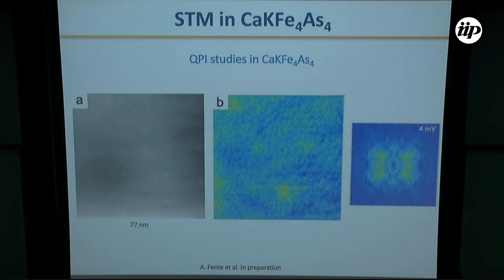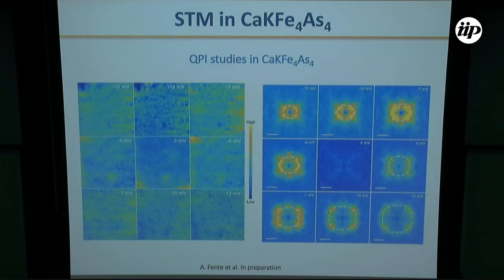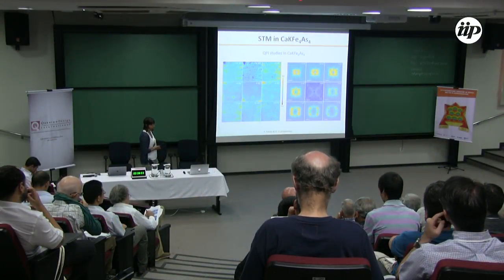We have made the QPI study in this sample. As I mentioned before, we first look at a large atomically flat region. Then we make conductance maps at different energies, and we analyze the quasi-particle vectors that appear in the Fourier transform. Here I show you the different images that we obtain as a function of energy between minus 13 millielectron volts and 13 millielectron volts, and the corresponding Fourier transforms, where we can identify a QPI vector that increases when we increase the energy. You can also note that at the Fermi level, the signal disappears due to the opening of the superconducting gap.